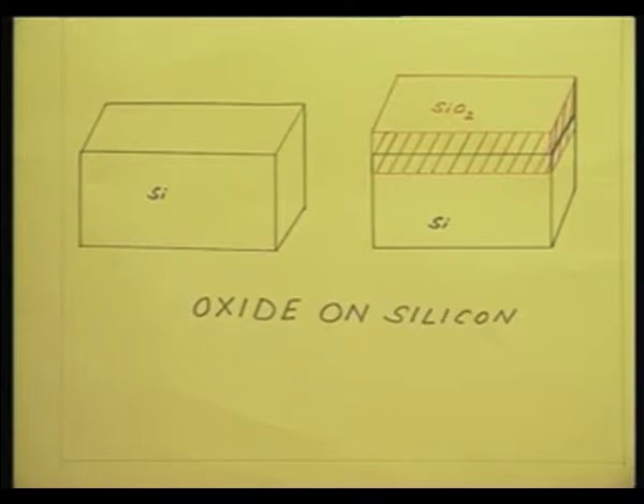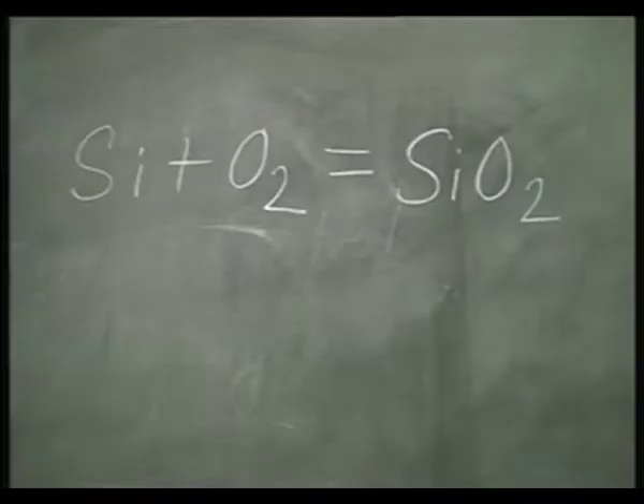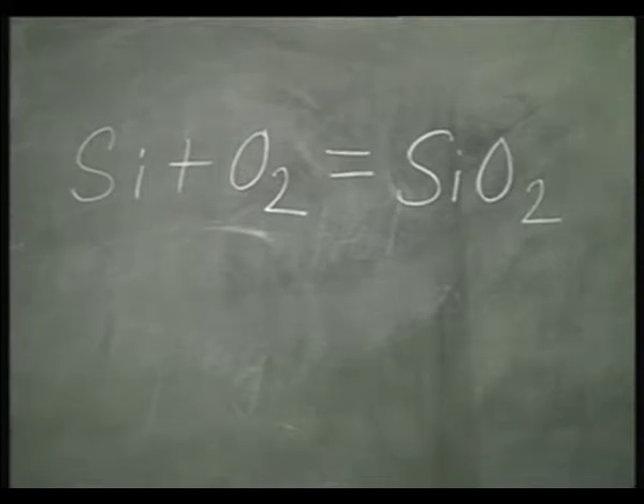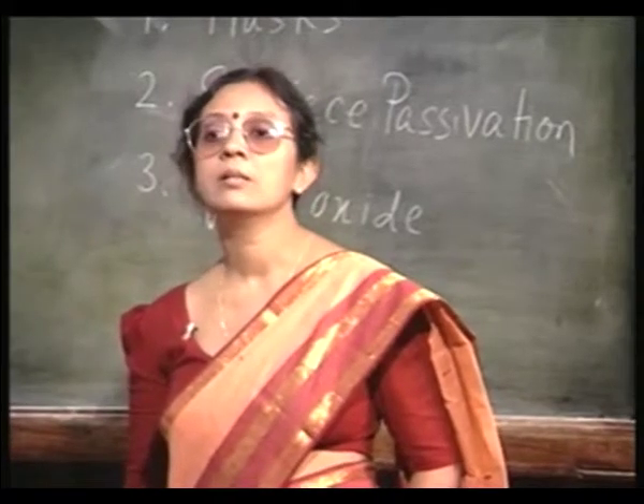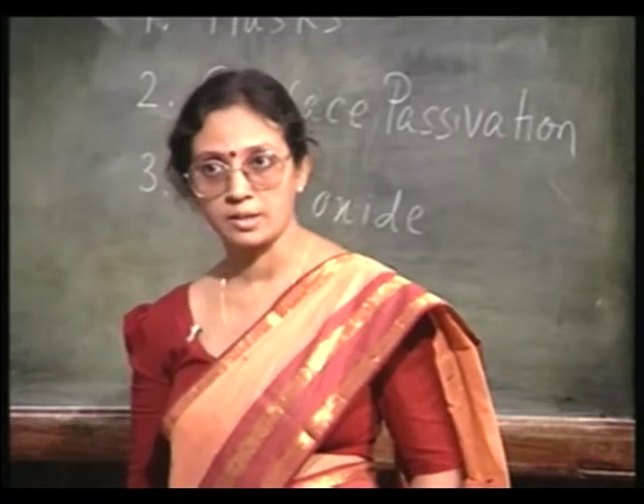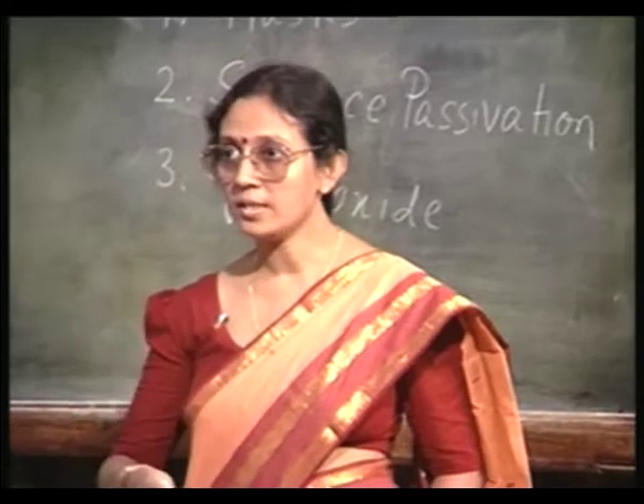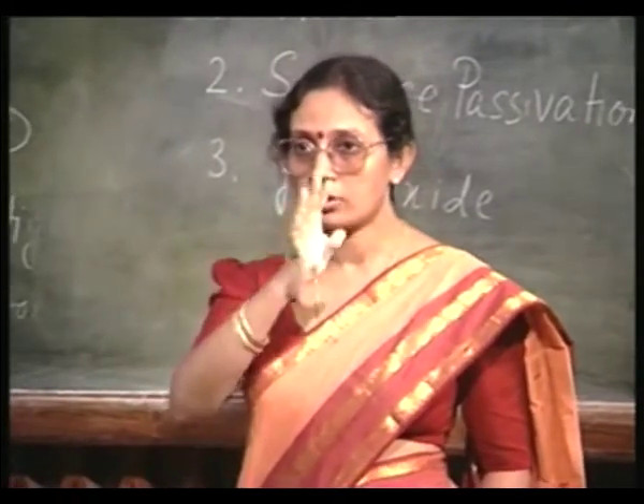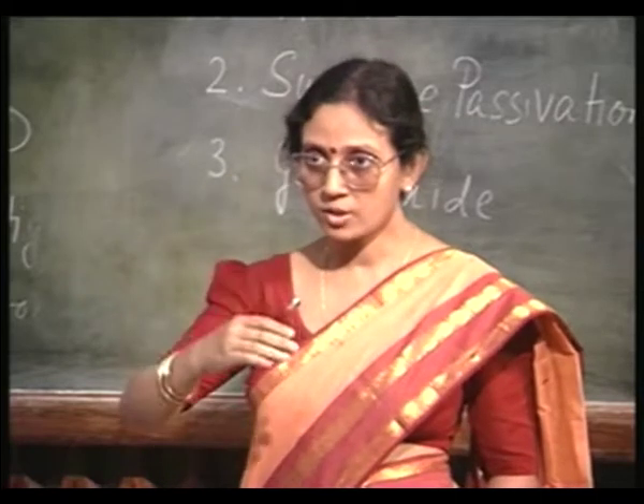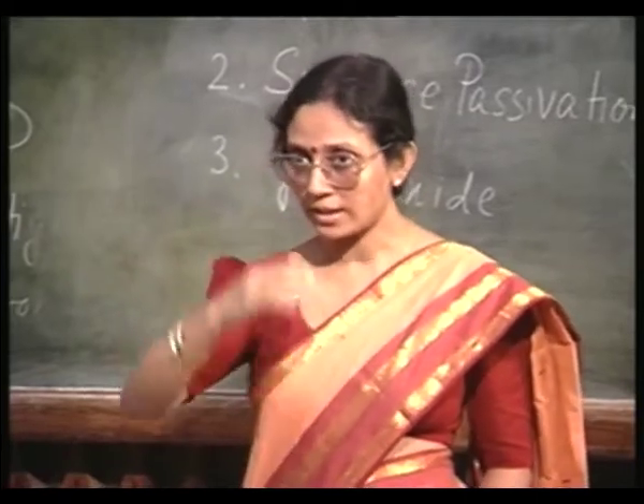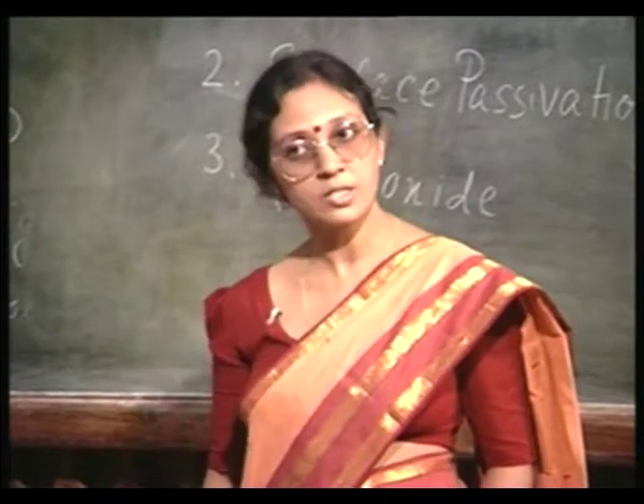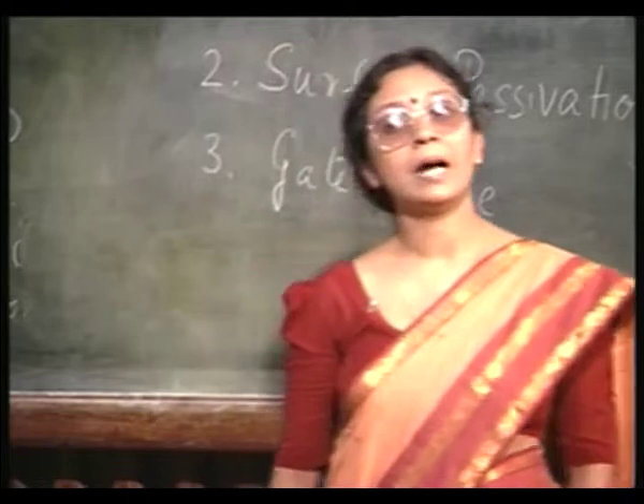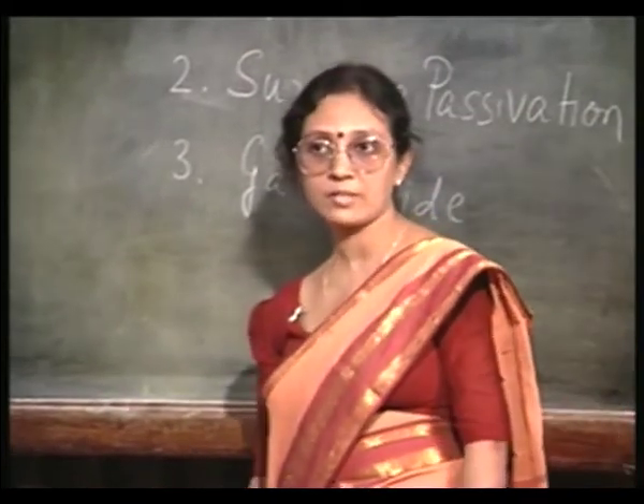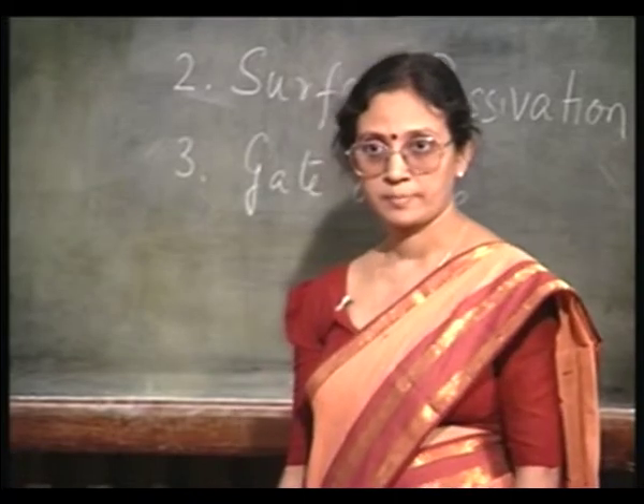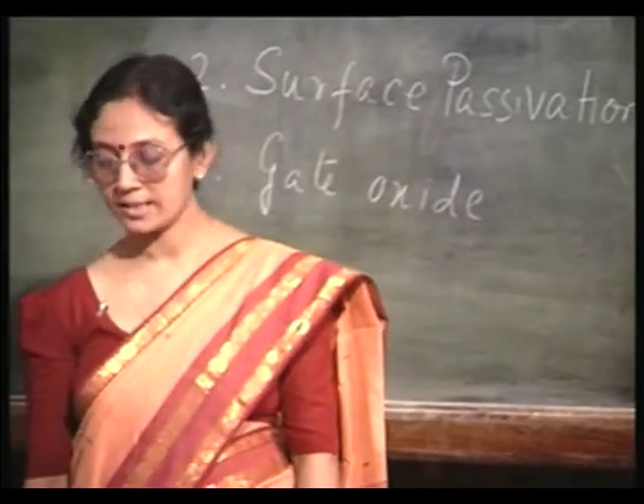If you look at this reaction, silicon plus oxygen is forming silicon dioxide. So, the logic is quite clear. Silicon is being consumed in order to form this silicon dioxide. So, obviously, the oxide is not staying atop the surface, it is consuming the silicon. So, that is why some part of it is going below and some part of it is going above. But by how much? How much is below the original surface, and how much is above the surface? We will do some simple calculations and see.